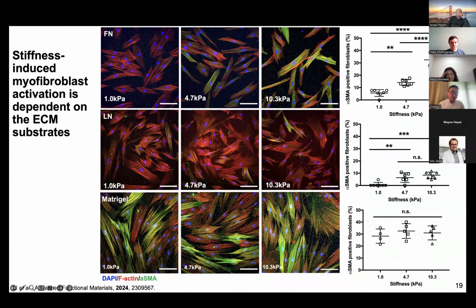So Matrigel contains a variety of different ECM proteins as well as growth factors. So you can see that in this case, regardless of the stiffness, you have most of them all activated. So again, this just shows us that cell function and behavior depend not only on the stiffness, but also on the ECM substrates they adhere to.